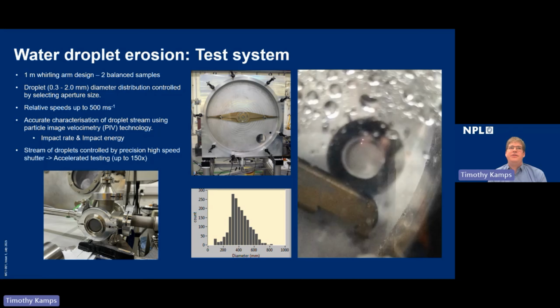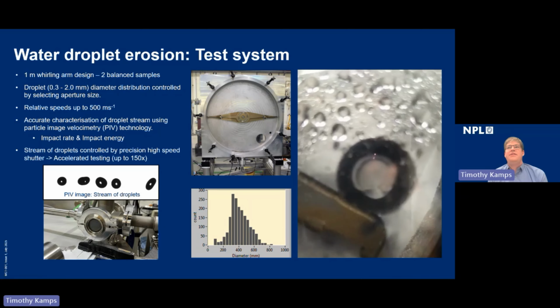For every test that we run, we characterize the droplet stream using a technique called particle image velocimetry. And we do this so that we can work out what the impact energy is, and with the impact rate, work out what the dissipated energy into the contact has been. In the center of the slide at the bottom, we can see a histogram of diameters against count for a particular nozzle. And the sort of image that we analyze in order to produce this is shown on the left-hand side.